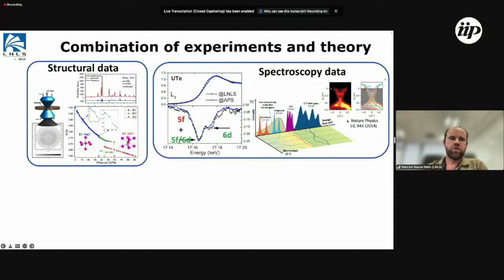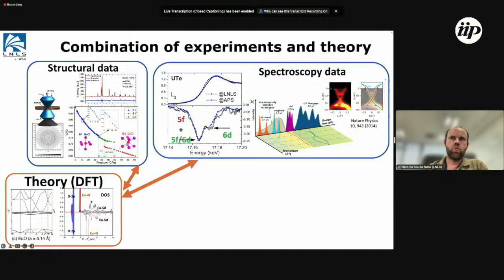So if we combine those, this is very much related to what other people or we can do with theory, for example DFT or ab initio calculations, where we can use this experimental structural information to do the calculation and estimate the band structure or the energy density of states, the projected density of states. So with this information we can correlate and help to analyze or corroborate the data, theory can support the experiments and the experiments can support the theory as well. So there is a combination of those.